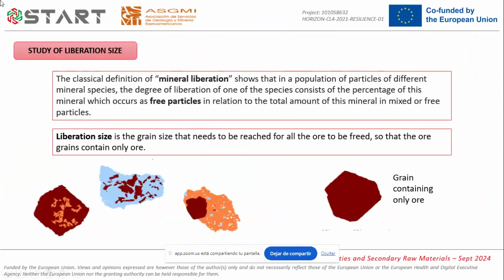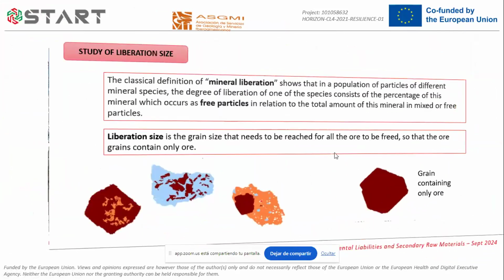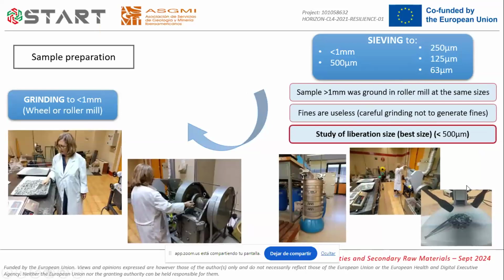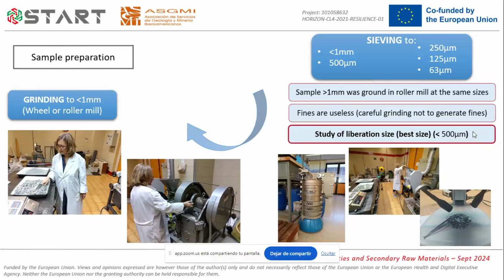But the most important thing here is to study which is the liberation size that we want to use in the assay. So apart from grinding to less than 1 millimeter, we try to get more material of the fraction with that liberation size. So during the grinding and sieving, the grains are always observed through the stereo microscope, and the liberation size is then decided. In our assays, it has been observed that for all the samples, the liberation size was the one lower than 500 micrometers.